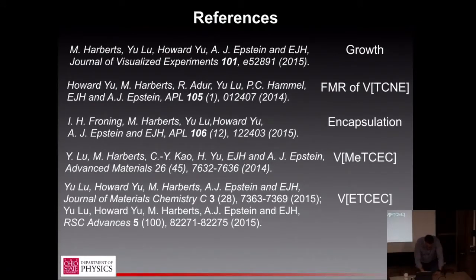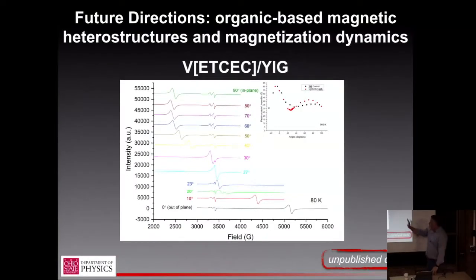But what we were trying: we have another version of this sample that has an aluminum layer between the organic and the YIG. And there's some very nice FMR work by Brett Heinrich and collaborators where they do an all FMR detection of spin pumping by seeing similar line width narrowing as they come into resonance. So here there's no interlayer, so it's more an evidence of exchange locking, I guess I should say.